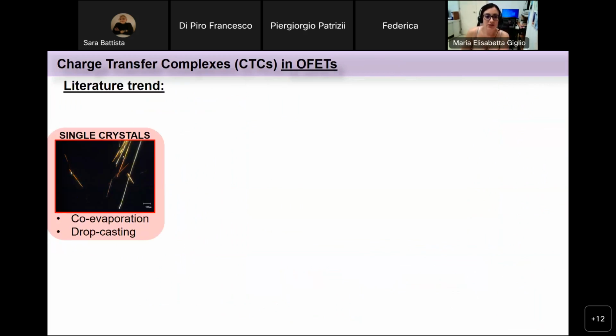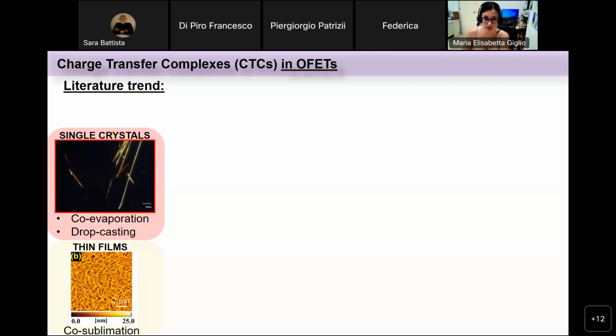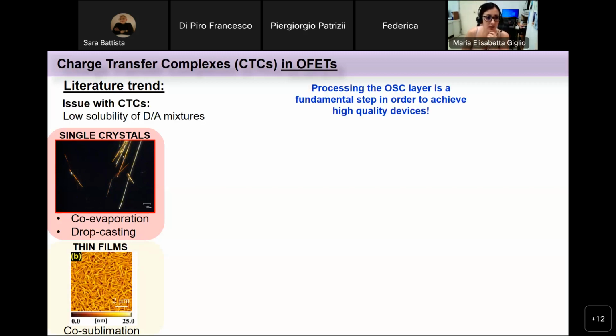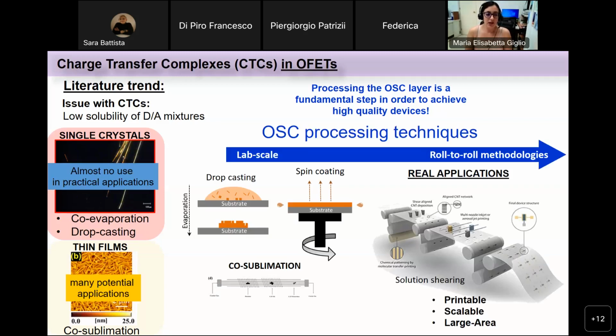But what about CTCs in transistors? So the literature trend is to see them used as single crystals produced by co-evaporation or drop casting, as well as thin films fabricated by co-sublimation. When we think about CTCs, basically we have to take into account the low solubility of the donor acceptor mixtures, and the processing of the organic semiconductor layer is a fundamental step in order to achieve high quality devices and in order to overcome all these issues about solubility. So basically, single crystals are almost of no use in practical applications, but thin films, yes, they have, because there are many potential applications when we think about thin films.